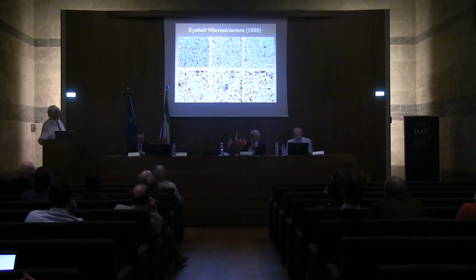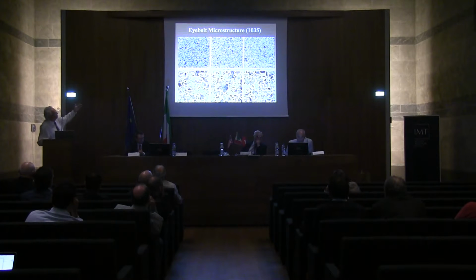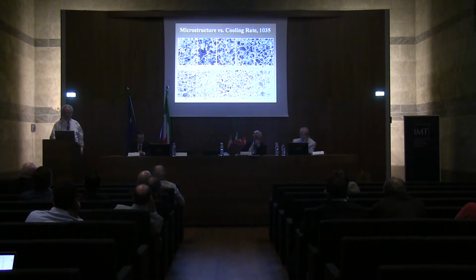And here's the actual microstructure of the eye bolt. Now, we're looking at two different magnifications. The top is 100x and the bottom is 500x. You can see the difference between the surface, mid-radius, and center: the surface has more pearlite, and as you go towards the center, you have somewhat less, and the pearlite is coarser in interlamellar spacing. So there's no tempered martensite in there, and of course there should not be if it's oil quenched.